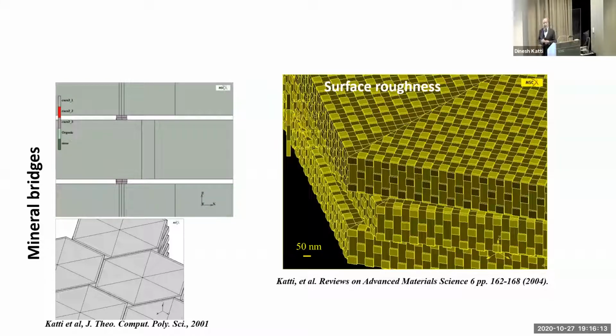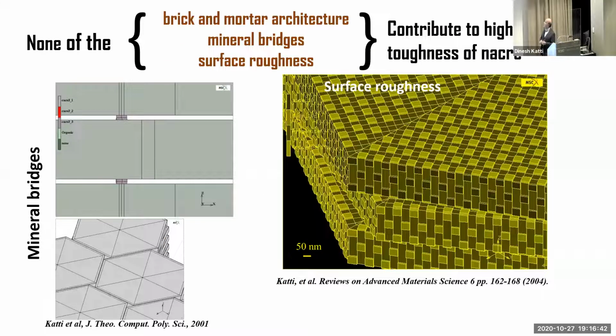And so we scoured the literature, and there were many speculations and theories that some features like mineral bridges, which are important for the growth of seashells, or surface roughness might be the reason why we have this high fracture toughness. So we built computational models of all these different features and tested them computationally, and found that none of these contribute to the toughness of nacre. And so basically, we were at a dead end here. We did not know what to do next.